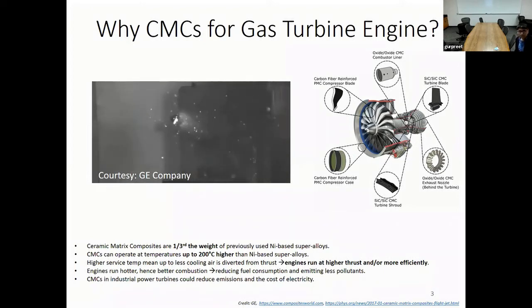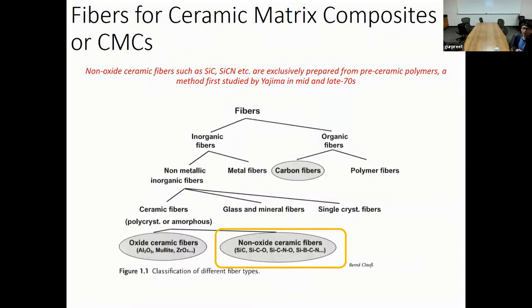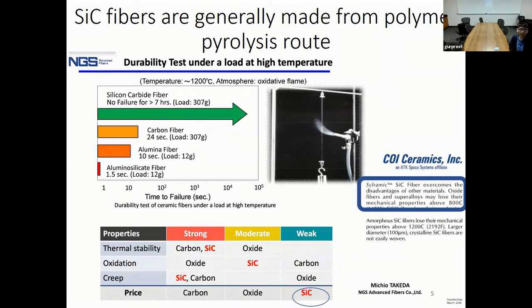So moving on, fibers are the most common or most desired form of reinforcement in not only CMC but also polymer matrix composite. Long continuous fibers are desired. So for high temperature application for CMC, you have basically two options. You can have oxide ceramics, these are metal oxides, or you can have these non-oxide ceramic fibers, which are generally silicon-based systems. Both of these are able to sustain high temperatures, both possess high temperature capability. However, the silicon-based systems, especially silicon carbide, has higher resistance to creep, as shown in this graph here. It's able to sustain higher load for longer periods of time, at the same operating temperature as oxide ceramics.